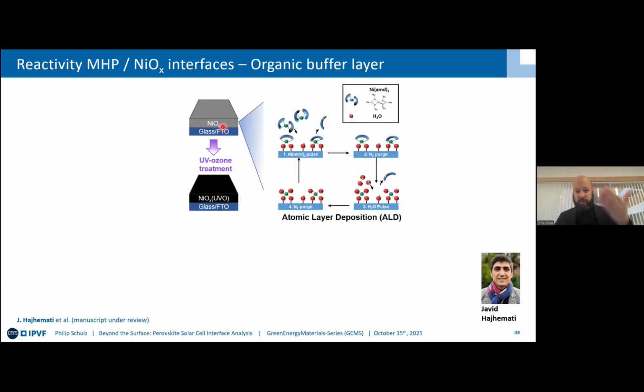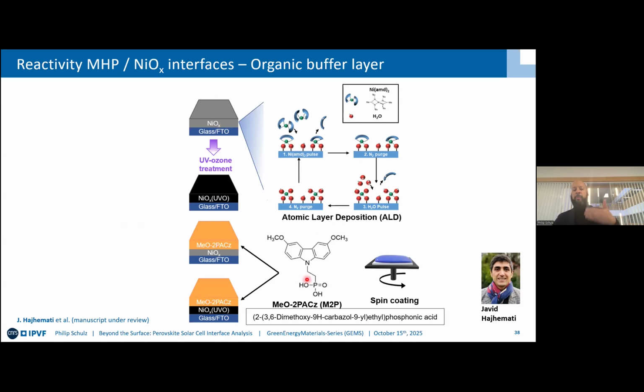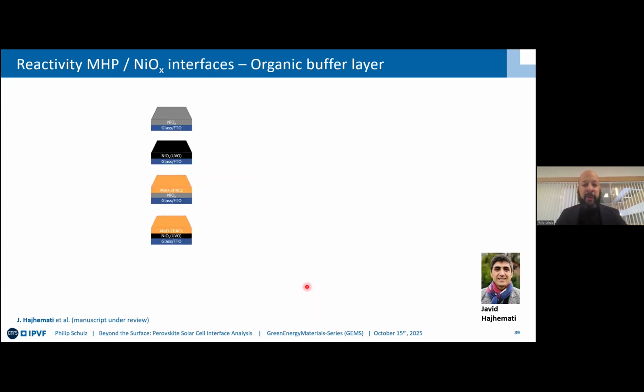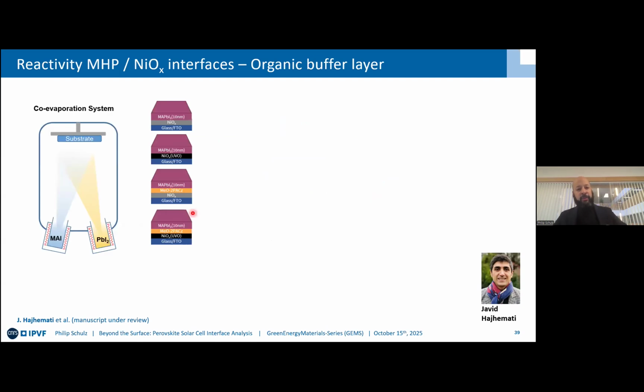So Javid Hajhemati actually used these ALD nickel oxide films, and now we went the other way around. So we tried UV ozone treatment, but then we also applied these very widely used MeO-2PACz surface modifiers that can make self-assembled monolayers, but in any case make an organic interlayer between the oxide and the perovskite. Then we actually took these surfaces and evaporated very thin layers, just 10 nanometers of MHPs, on top.